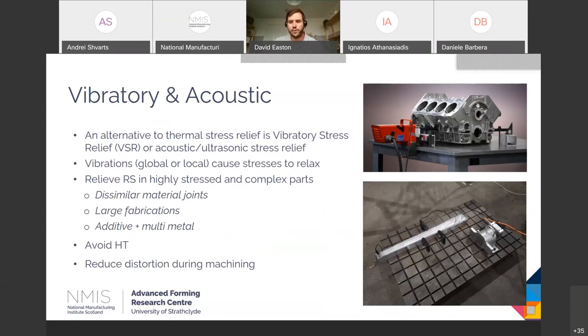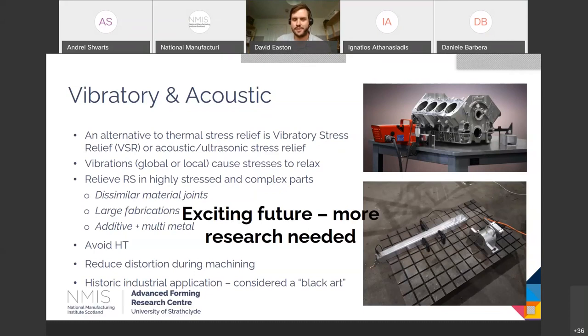This is a technology that's commonly applied prior to machining. It has existed for decades and decades, particularly over in the States, and it's been used not directly to reduce residual stresses per se, but to reduce distortion that occurs during machining. And the reason that there's less distortion is because stresses have been relieved. Exciting technology, and something that needs a lot more research, and something that we're working on quite often here at the centre.